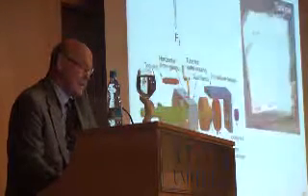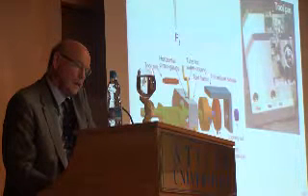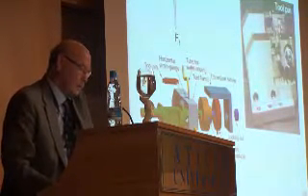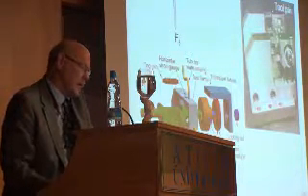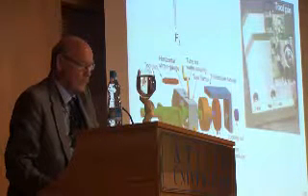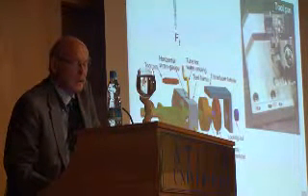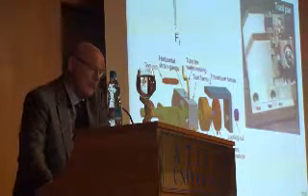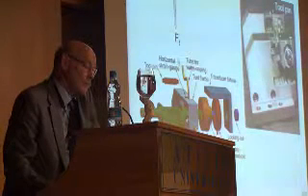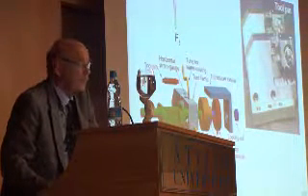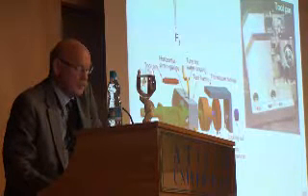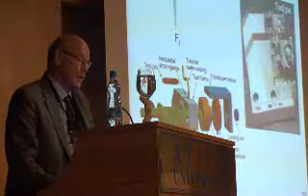As simulative test, we start with the bending under tension, where we use the principle developed by Weinmann, having thin wedges here as supports to this cradle. In the cradle we have a pin tool, and we have developed the test further. He measures only the vertical forces by strain gauges on these horizontal webs and the horizontal forces down here. But this requires for measuring a small quantity by subtracting a large measured force from a large measured force to get a small force. And we introduced a torque transducer for measuring the friction directly instead.